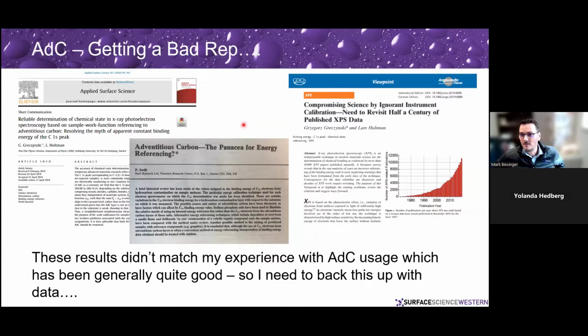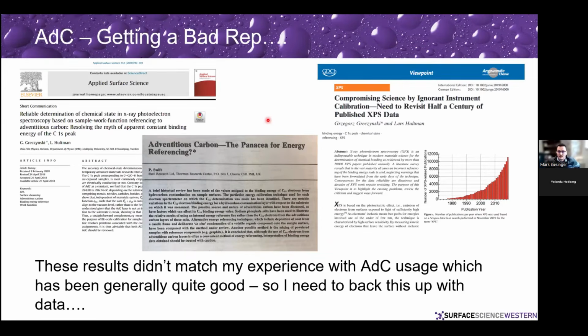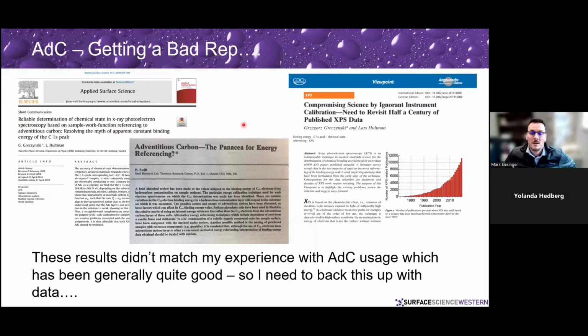And again, I have now 30 plus years of XPS experience, probably about 33 years now. And we've been using adventitious carbon effectively for thousands and thousands of samples, running on instruments that we've been able to make that charge reference work, so that we were able to pull out chemistry routinely and effectively, corroborated by other instruments and corroborated by what it should be in other science techniques. And so for someone to say, you need to throw out all this data, you can't use it, doesn't work, it did not really jive at all with my experience.